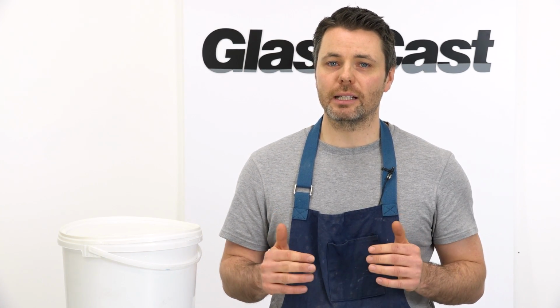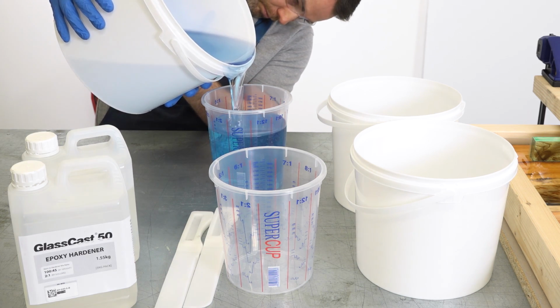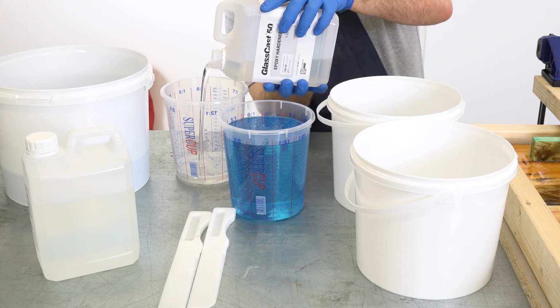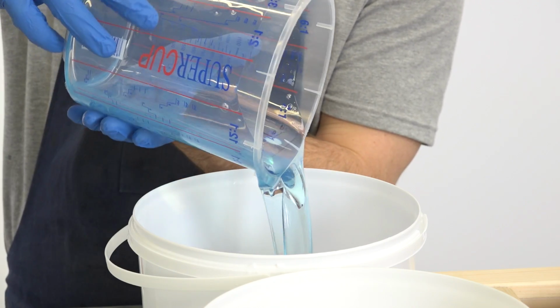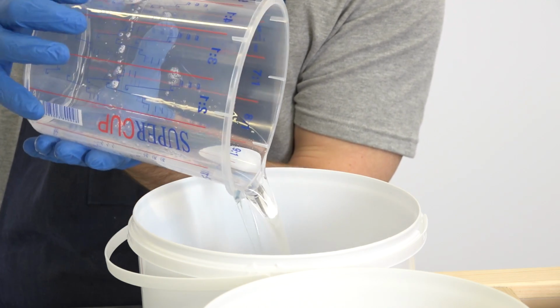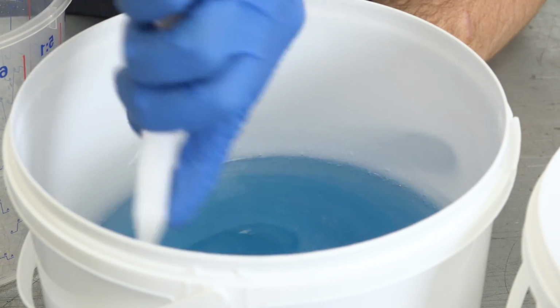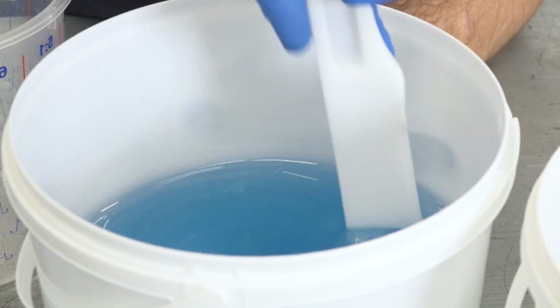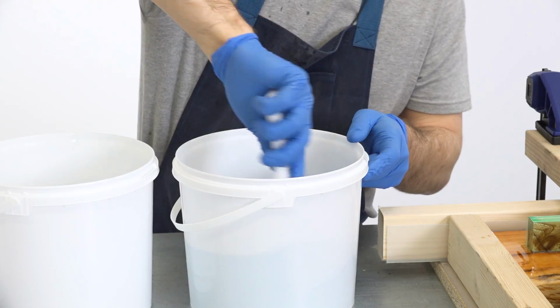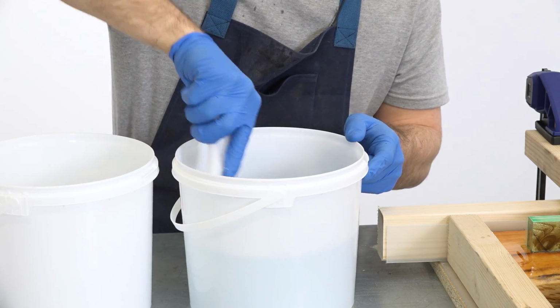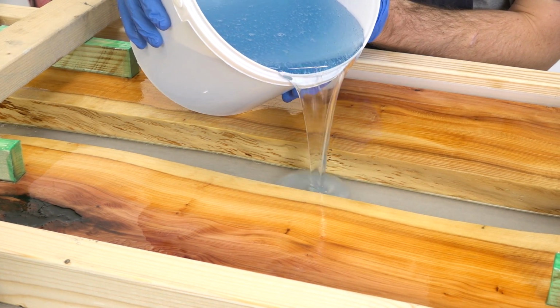Because the depth of our table is 40 millimeters, I'm actually going to split the main pour into two separate stages, allowing the resin to cure to its B stage between each pour. This will avoid the risk of the resin overheating whilst it cures, which is a problem that we could face if we tried to do the main pour all in one go. We'll keep following the double potting procedure for all of the remaining resin mixes. The 2:1 by volume mix ratio makes this next mix simple. I'll mix up 3 litres of resin in total, so 2 litres of resin and 1 litre of hardener to bring me just past the halfway depth.